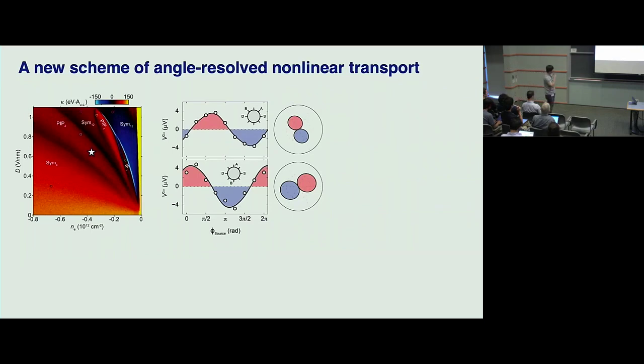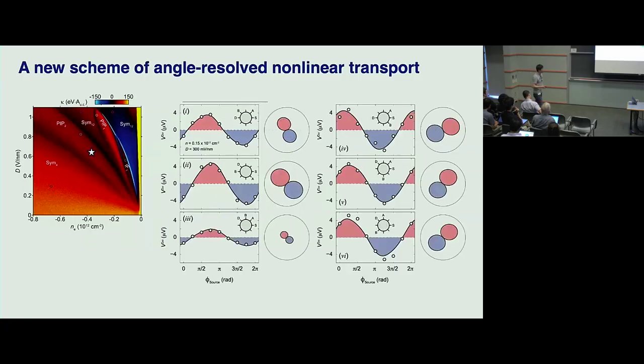This is also another thing our theory collaborator realized, that you don't have to be confined to these two configurations, right? There's nothing special about longitudinal and parallel transverse in a disk sample. You can, in fact, take any leads as source, take any other leads as drain, and then measure a voltage difference across any two other leads. That will give you 830 points. I was extremely reluctant to do that because usually that's what's going to expose the downside of the sample. Right? But my students were brave enough to do all of that.